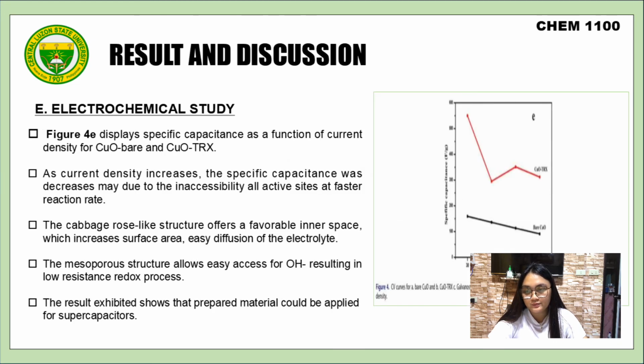Next slide, please. Figure 4E displays specific capacitance as a function of current density for copper oxide bare and copper oxide TRX. As current density increases, the specific capacitance decreases, due to the inaccessibility of active sites at faster reaction rates. The cabbage rose-like structure offers a favorable inner space, which increases surface area and allows easy diffusion of the electrolyte, and the mesoporous structure allows easy access for OH, resulting in a low resistance redox process. The results show that the prepared material could be applied for supercapacitors.